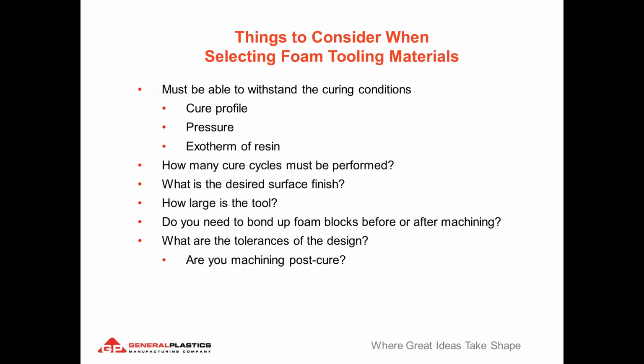So things to consider. These are all questions you should be asking yourself and discussing with your suppliers before you select a foam material for your soft tooling. What type of cure profile does your desired composite matrix resin require for curing? What types of pressures are going to be exhibited on the substrate? What's the exotherm of the resin expected to be? How many cure cycles must be performed? Is this a single cure prototype part, or is this one you expect to get two pulls off of it, or 10 pulls?